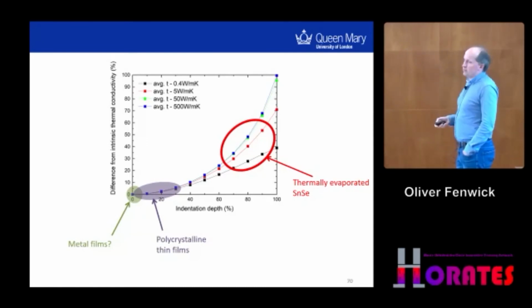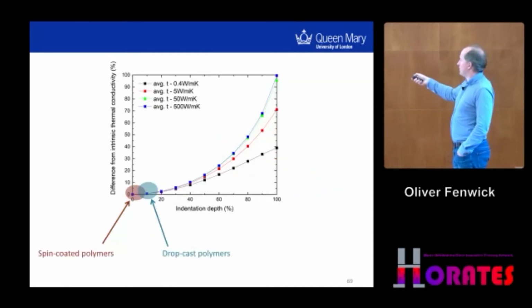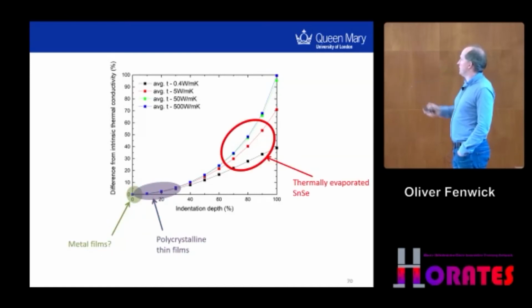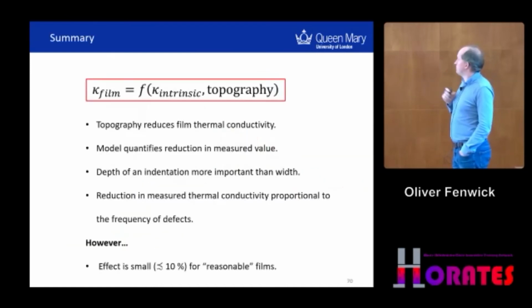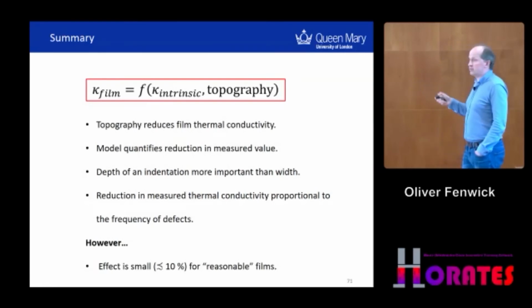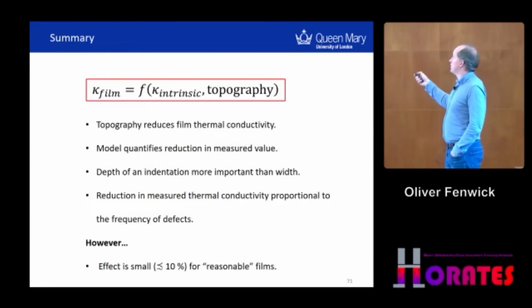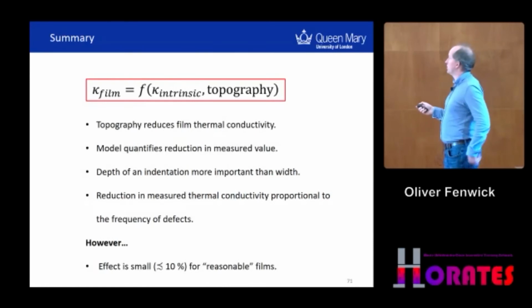That's why the methylammonium lead iodide gave a low value, and that's why I can trust our measurements on polymers and polycrystalline films. The key message from that is that the thermal conductivity of a film is a function of the intrinsic thermal conductivity of the material it's made of and the topography. Okay, maybe it seems fairly obvious put like that, but you need to bear that in mind. If you have thermal constrictions in your film, you will measure a lower thermal conductivity. You need to make sure it's not too much lower.